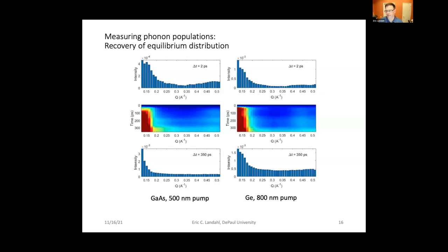The configuration of this experiment was made to get as broad a region of reciprocal space at as high resolution as possible. And we did have fantastic temporal resolution in this very early run at the XFEL. Other groups frequently do look at what those frequencies are, and then try to match both the frequency and the wave vector with a particular phonon mode. We have not done that, but you'll notice that these stripes are quite uniform all the way across. That's definitely an interesting aspect of the data, and again, it's very repeatable. Okay, thank you.